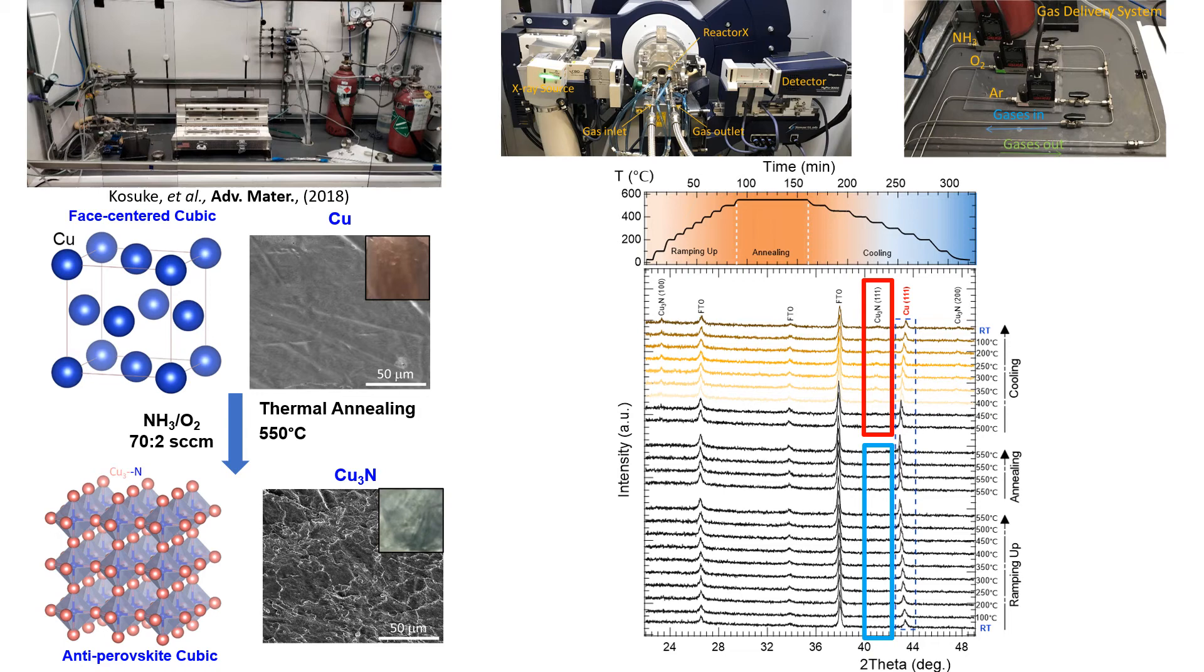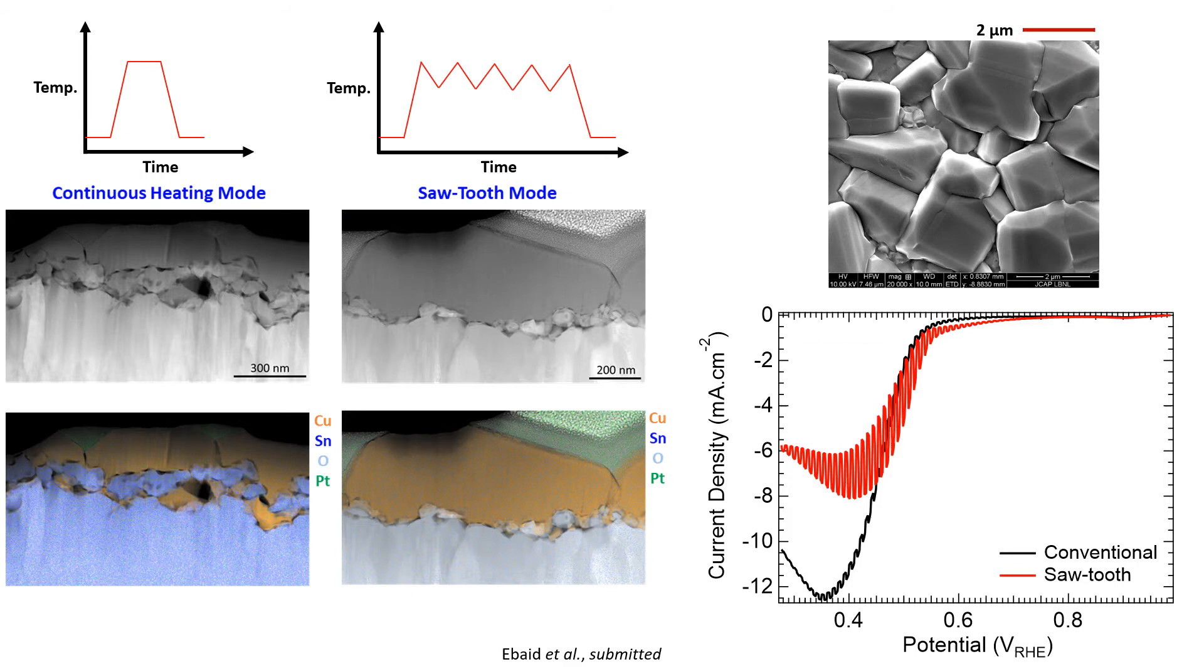As such, we developed what we call a sawtooth heating mode, and in comparison to the continuous heating mode, results in larger grains and improved grain quality. To date, there had been no reports of photoactive copper nitride in the literature to the best of my knowledge. The reason seems to be related to having metallic copper inclusions or copper interstitial defects. This sawtooth heating, however, gave us the first significant glimpse of photocurrent, albeit with a significant amount of dark current.